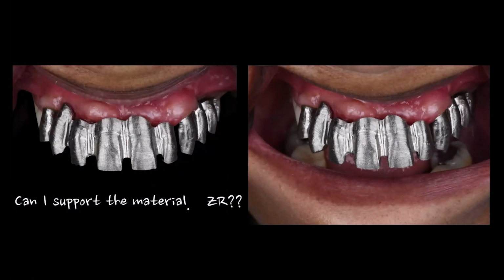So yes, I would have had the height that I needed for zirconia. I wouldn't have necessarily had the thickness I needed for it. And the other real reason is, where the screw access channels were, I would have had a very thin tube of titanium and a large amount of zirconia hanging off that, which I didn't really like either. So I chose to go old school metal ceramics.